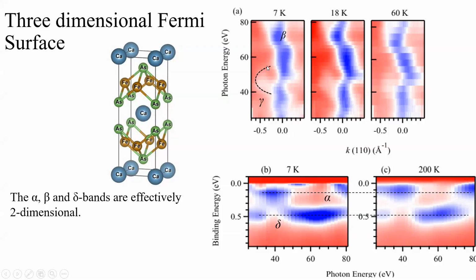However, the gamma band position moves as a function of photon energy. It means that the gamma band has a significantly higher kz dependence in comparison to the alpha and beta bands. So cobalt doping is also introducing kz dependence in the gamma band, which was effectively two-dimensional before doping.